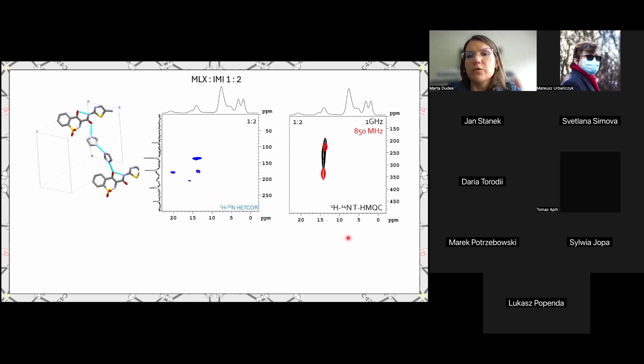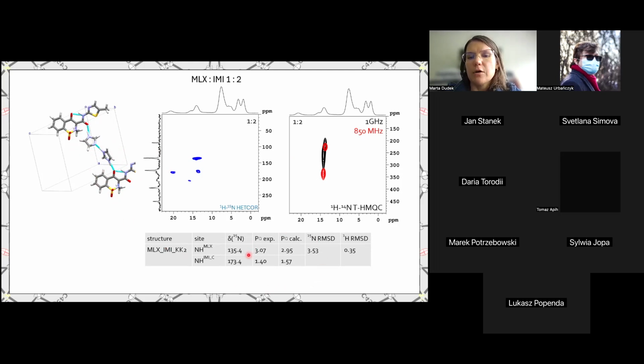Again, nitrogen 15 and nitrogen 14 measurements, from which we were able to determine that one of the imidazole molecules is indeed in its neutral form, but there is a proton transfer from meloxicam to the other imidazole molecule. So it's actually not a co-crystal, but well, one may say a salt co-crystal, in which only one imidazole molecule is protonated and the other is neutral. And finally, the comparison of the experimental and calculated PQ values as well as RMSD values in excellent agreement with what we saw.